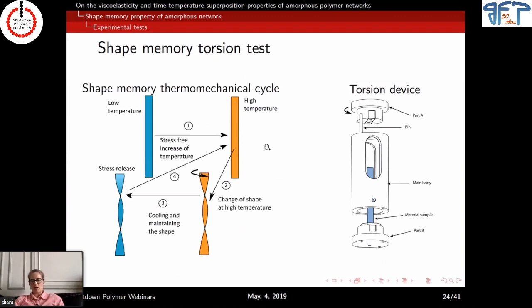So we decided to build a torsion device that would help us look at change of shape with large transformation, rather small deformation, but large transformation, and quantitatively, while we raise the temperature, look at the recovery in terms of temperature. So the idea was to have a slender rectangular sample, raise the temperature, apply a 360-degree torsion, cool it down, and then look at its recovery while we heat the sample.